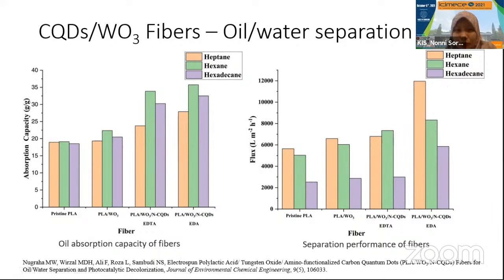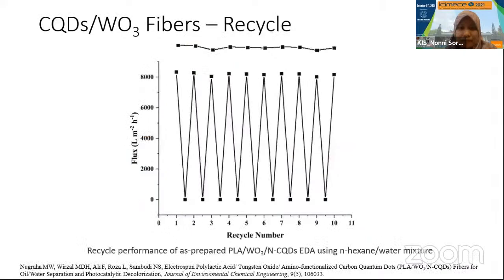Okay. Then we want to see whether the fiber mat is stable enough to do its job if we reuse it several times. Okay. And then we try to recycle the fiber around 10 times and we still get a consistent flux, of more than 8,000 liters per meter square hour. Okay, so we use this recycle performance for the mixture of the hexane and water. So from here, we can see that the fiber that we made is quite stable to be used around 10 times to separate the hydrocarbon from water.